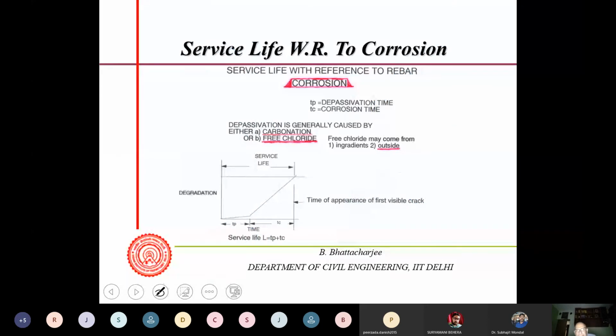So, I'll have maybe another slide where we'll see that. They are not dangerous because their density is similar to that of the steel itself, close to that. And they are a thin, dense layer that does not allow more steel to get dissolved. That's called passive condition. If the chloride is coming from outside, then it requires some time for chloride to penetrate through the cover. But if it's there in the ingredients, then this will be zero. Tp will be zero. After that, corrosion starts, and someday the crack will appear on the surface of the concrete, and we call it service life period has reached. First appearance of first crack.